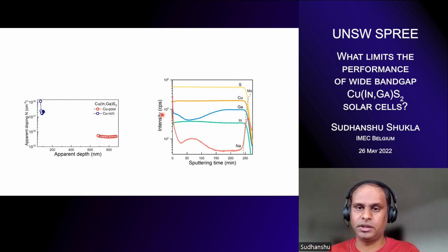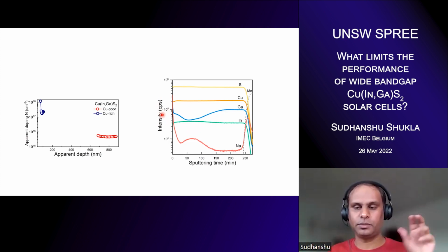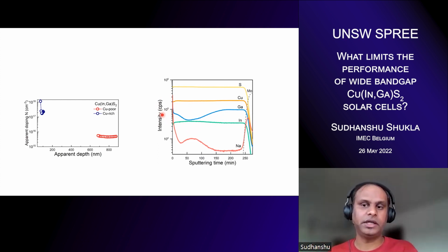So this is from the SIMS. And yes, the morphology becomes rough and there's some sort of recrystallization going on, which we are still studying from cathodoluminescence mapping. We are checking the grain boundaries and within the grains, if the different absorbers with different copper compositions are strikingly different in terms of crystal quality. We are investigating this at the moment, but there is a segregation of this gallium species at the surface. Which might not be good, by the way, because then you can have a barrier for electron flow. So that also needs to be played in the end. This needs to be controlled when you are doing synthesis.